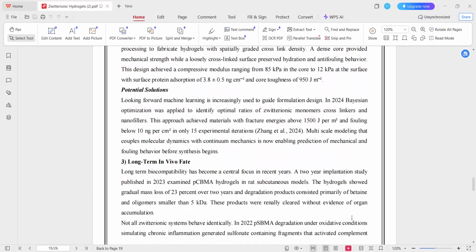Looking forward, machine learning is increasingly used to guide formulation design. In 2024, Bayesian optimization was applied to identify optimal ratios of zwitterionic monomers, crosslinkers, and nanofillers. This approach achieved materials with fracture energies above 1500 joules per meter square and fouling below 10 nanograms per square centimeter in only 15 experimental iterations. Multiscale modeling that couples molecular dynamics with continuum mechanics is now enabling prediction of mechanical and fouling behavior before synthesis begins.